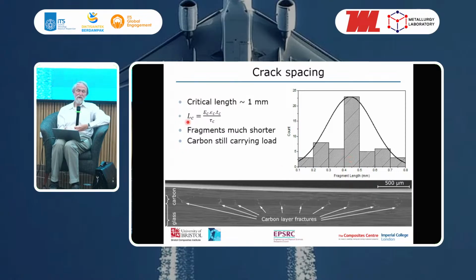And the critical length is related to the modulus of the carbon fiber, the strain to failure, and the thickness, divided by the shear strength of the epoxy. Because it's the distance it takes to reload the fiber through shear at the interface as you go away from the fracture. And if you do that calculation for this set of materials, you find the critical length is 1 millimeter. So what that would mean is, in tension, you would not be able to get cracks closer than 1 millimeter. Because once you get to a 1 millimeter fragment spacing, then you can't get enough additional load into the fibers to break it. But here we're seeing that the fragment length is substantially less than this 1 millimeter.